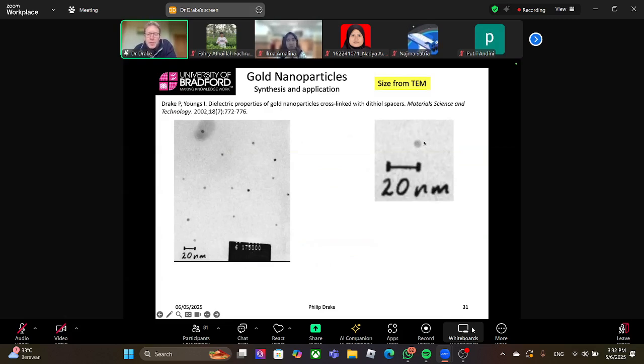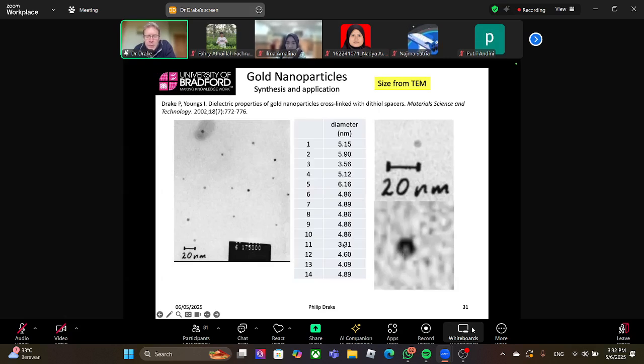How do we measure the size? We can use SPR peaks and UV-Vis. The best is using TEM. With TEM, we physically measure the size of the particle. We know the scale bar, we measure the size of the particle. We can get a ruler out, measure it. We can get a whole list of particle sizes. Just measure lots of particles using software or using a ruler, list them all down. Once you get a whole range of particles, you can then take the average and you can work out the standard deviation. So from these particles, we have an average size of 4.79 nanometers with a standard deviation of 0.77. This is what we need to characterize our particles, the average size and the standard deviation.